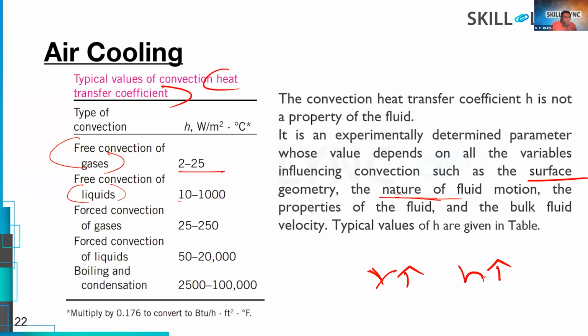Similarly for forced convection, it is multiplied by 10. You can see 25 to 250 for gases, and for liquids, 50 to 20,000. And during boiling and condensation, the phase change process, this h will be dominating, greater than thousands, like 2,500 to 1 lakh. So these are the different ranges based on the convection, the type of fluid, bulk velocity, and geometric profile.